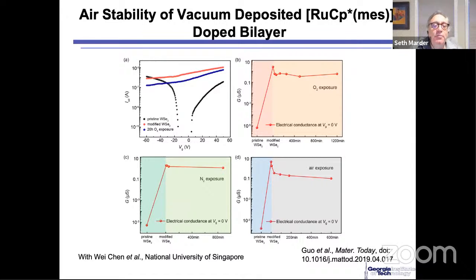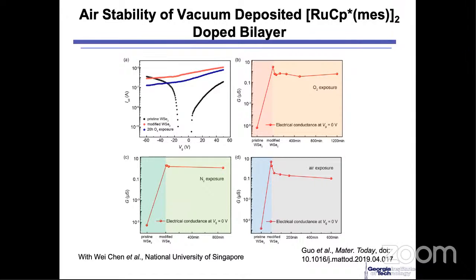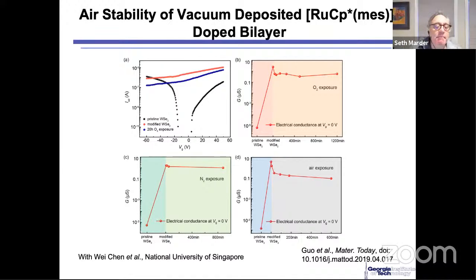Okay, they dope a bilayer, and they measure the conductance, not the conductivity. And what you can see is that when they dope this material, it goes from having a conductance of 10 to the -5 to, on the order of, about 4 to 5 orders of magnitude higher.